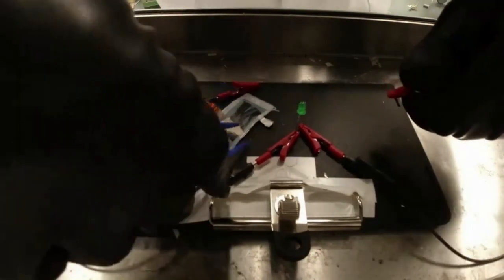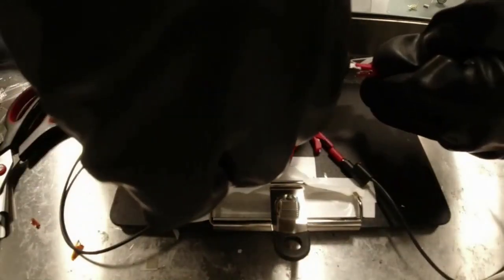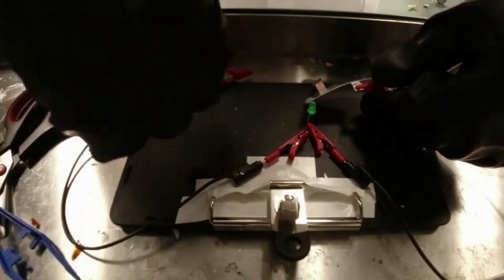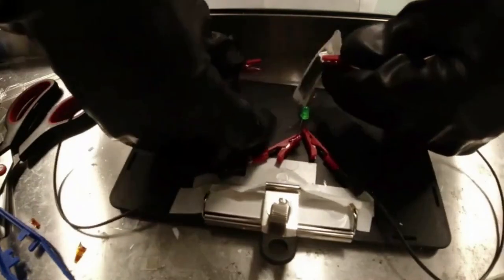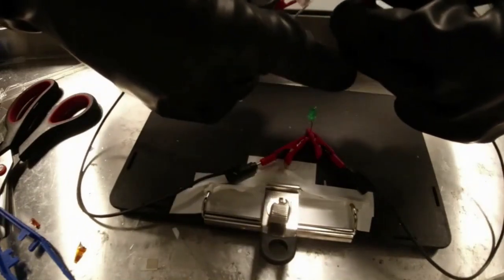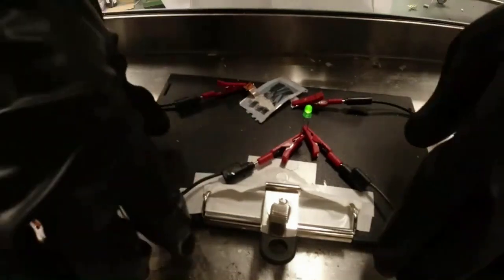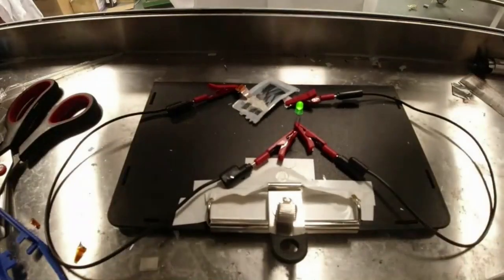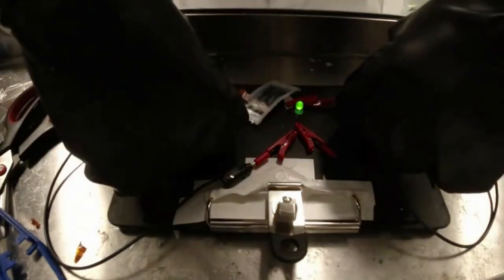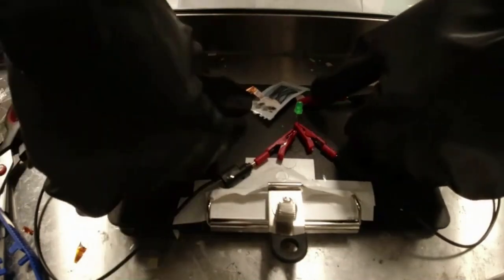The battery has an energy density of 24 Wh per kilogram, meaning approximately 20% capacity compared to comparable lithium-ion batteries currently available. But since the weight of the vehicles can be greatly reduced, less energy will be required to drive an electric car, and lower energy density also results in increased safety. And with a stiffness of 25 GPa, the structural battery can really compete with many other commonly used construction materials.